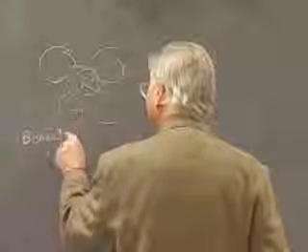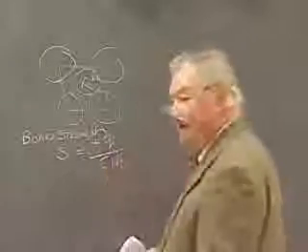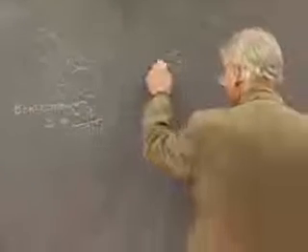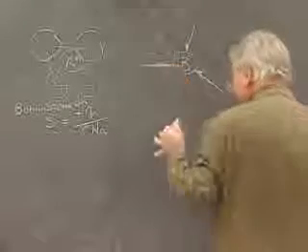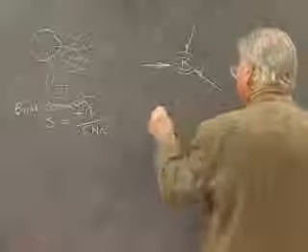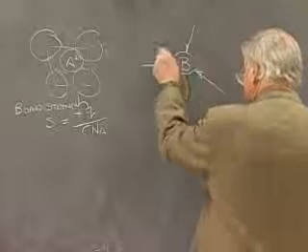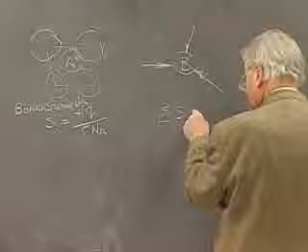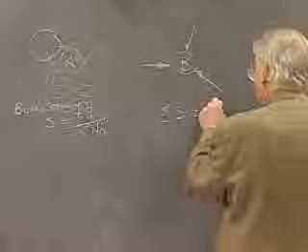He said, let us look at the coordination number of the cation A and look at the coordination polyhedron, and let's define as the bond strength S the ratio of the cation charge, Q, divided by the coordination number of A. And then he said that in a stable structure, if we look at the anion, the sum of all of the bonds donated to, he visualizes the charge being donated to the anion, the sum of all of the bonds from the same cations or from different cations, if that's the nature of the structure, should be equal to the charge of the anion.